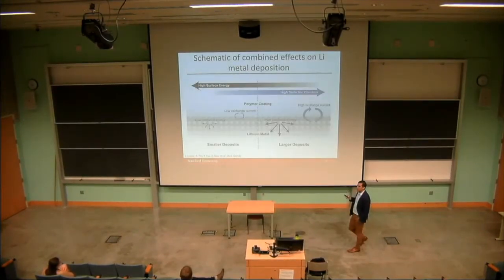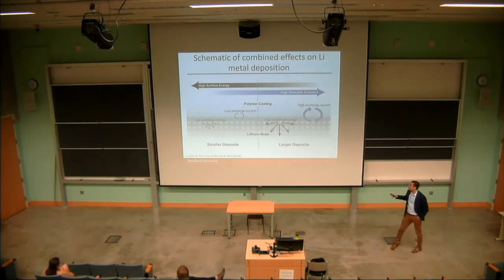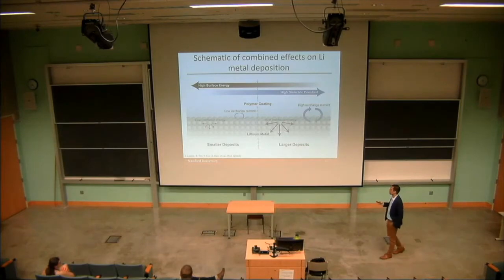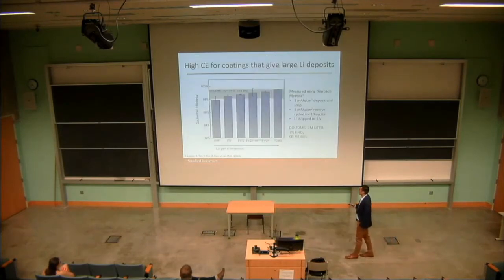To put that in a bit more of a schematic or diagrammatic way, you can see again here that low surface energy and high dielectric constant lead to high interfacial energy and high exchange current, respectively, which gives you larger deposits from that scaling analysis. And then again, high surface energy and low dielectric give you low exchange current, low interfacial energy, which lead to smaller lithium deposits.